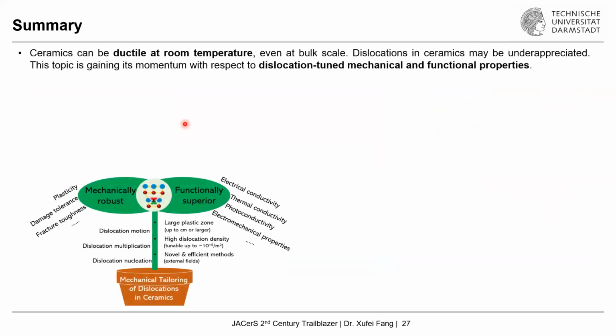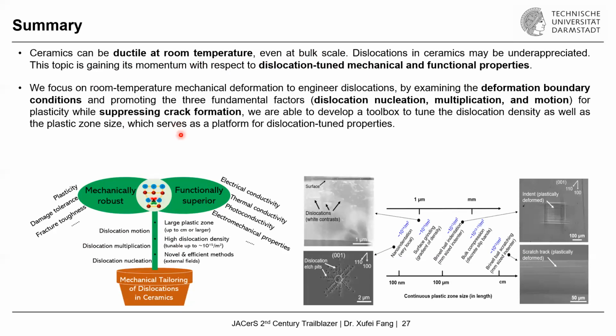So to quickly summarize, I would say ceramics can be ductile at room temperature, contrasting the conventional picture that ceramics are brittle, and even at bulk scale. So dislocations in ceramics may be underappreciated, and this topic is also gaining momentum with respect to dislocation-tuned mechanical and functional properties, as you can see here. So in this talk, I showed you some of the details and counterexamples where we focus on room temperature mechanical deformation to engineer dislocations, particularly by examining the deformation boundary conditions, looking at dislocation nucleation, multiplication, and motion, as well as suppressing the crack formation. We can actually achieve plastic zone sizes up to centimeters in length, and also with a density even approaching 10 to the power of 15 per square meter, which really serves as the platform for a lot more dislocation-based studies.